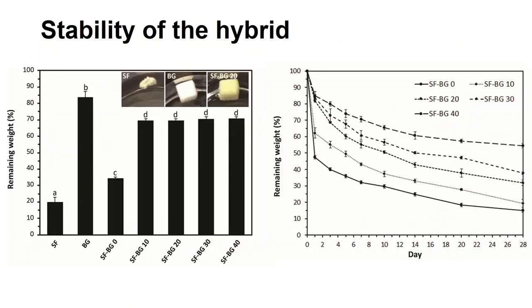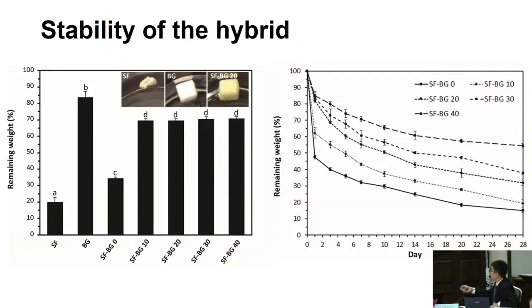So we tested for stability again. And what we found is that after one day, silk fibroin lost a lot of the weight. From 100%, after one day, the silk fibroin scaffold lost like 80-something%, whereas bioactive glass is quite stable. And this is when we didn't use the cross-linker. The weight loss is about 65%. After that, we cross-linked the two networks together. What we got is that after one day, they lost only about 25% of the weight. So the stability is increased by cross-linking with GPTMS.